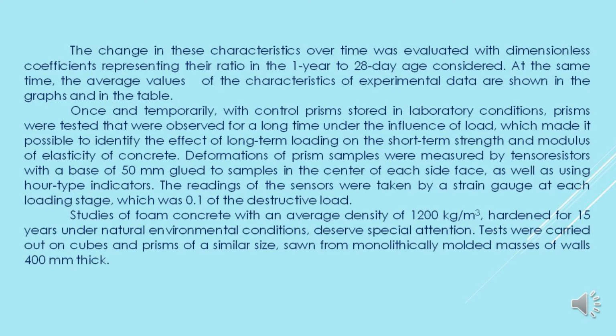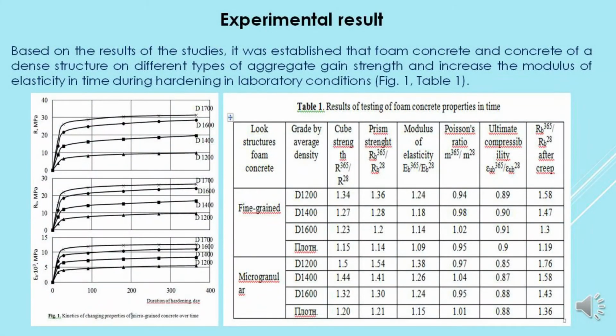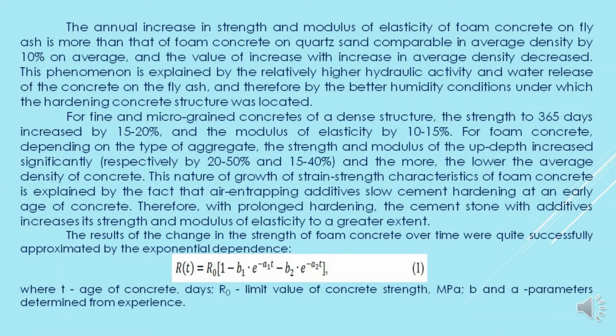Studies of foam concrete with an average density of 1200 kg/m3, hardened for 15 years under natural environmental conditions, deserve special attention. Based on the results of the studies, it was established that foam concrete and concrete of a dense structure on different types of aggregate gain strength and increase the modulus of elasticity in time during hardening in laboratory conditions. The annual increase in strength and modulus of elasticity of foam concrete on fly ash is more than that of foam concrete on quartz sand, comparable in average density, by 10% on average, and the value of increase with increase in average density decreased.